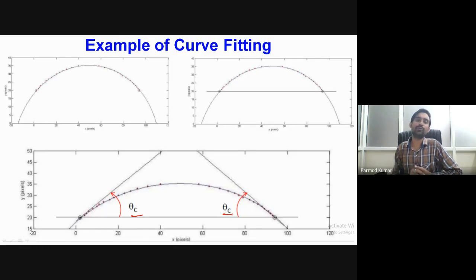Generally, we take the experimental snapshots, and these are further processed with image analysis and edge detection techniques to find the periphery of the droplet. The periphery of the droplet is then fitted to a curve with a polynomial fit, and from that curve we find the equations of the tangents at the contact point, and from the equation of the tangent we find the angles.